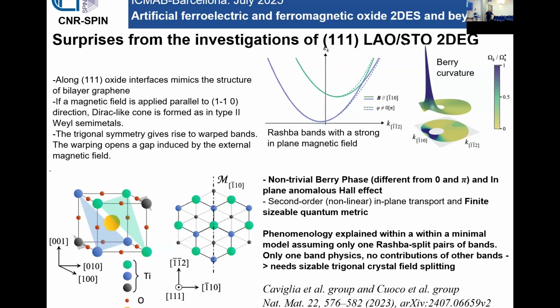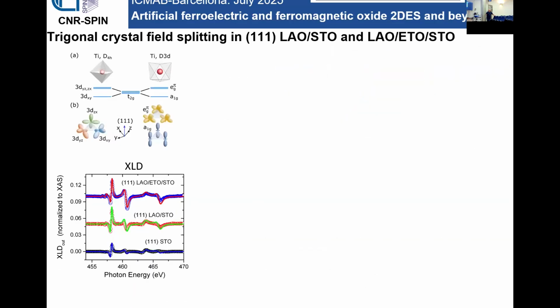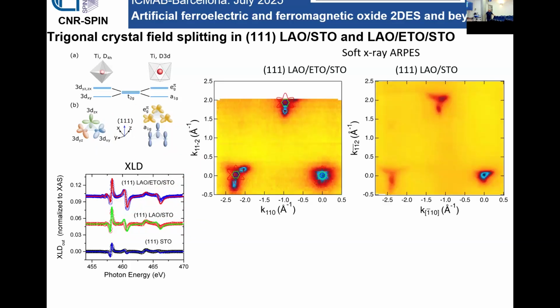However, for everything to be described in this simple picture, you need these Kramers bands to be well separated from all the others. You have to work in a single band regime. So you need the trigonal crystal field splitting between the lowest band and the higher band, which is very important in the physics of this system. On the other hand, one of the problems is that we measured, a long time ago, the trigonal crystal field splitting of the 111 LaO-STO and also our 111 LAO/ETO/STO, and we found that the splitting is very small in the 111 LaO-STO.